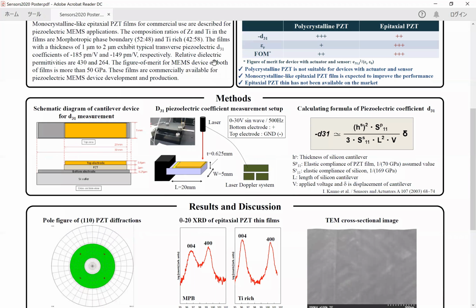In order to characterize the transverse piezoelectric response of the low-K PZT thin film material, a laser Doppler vibrometer measurement or LDV technique was employed. This is a schematic diagram of cantilevers with a PZT capacitor for the measurement, and this is a measurement setup.